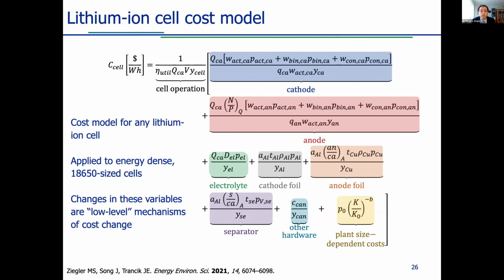We have different sections for the different components of the battery, and the variables in our cost model reflect the underlying chemistry and engineering, from the specific capacities of the materials to the thickness of the separator. And we also pull out some variables that apply to all of the subcomponents. And this model can be applied to any type of lithium-ion cell. However, in our work, we want to limit our comparison to control for a few factors. Recall how cells diversified over time. We want to control for changes that might have been implemented to make cells better for new, different applications. So we're going to focus only on energy-dense cells, those which aim to provide as much energy as possible in a given volume. And we will control for this volume by comparing cells of only the same size and shape, 18650 size cylindrical cells. Given these controls, we can then examine changes in these variables.